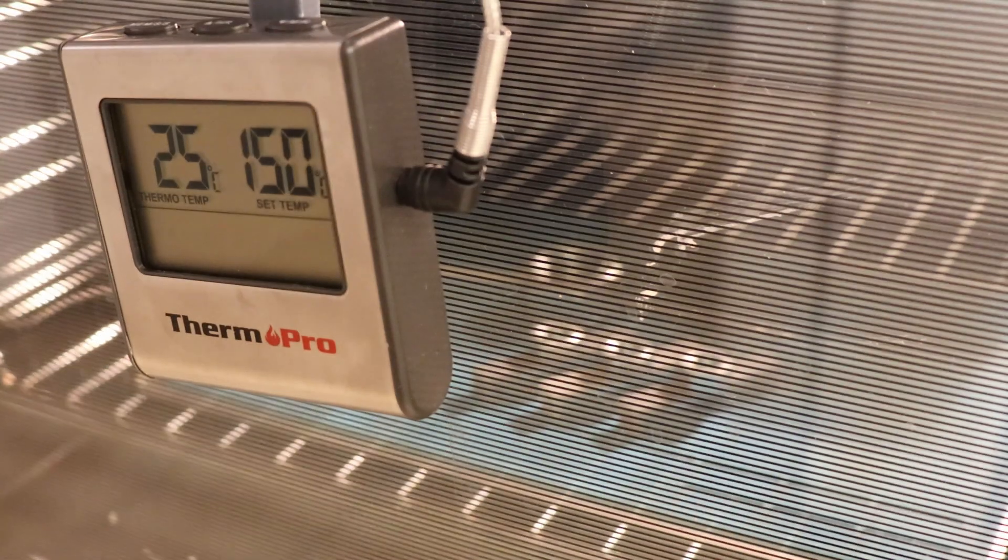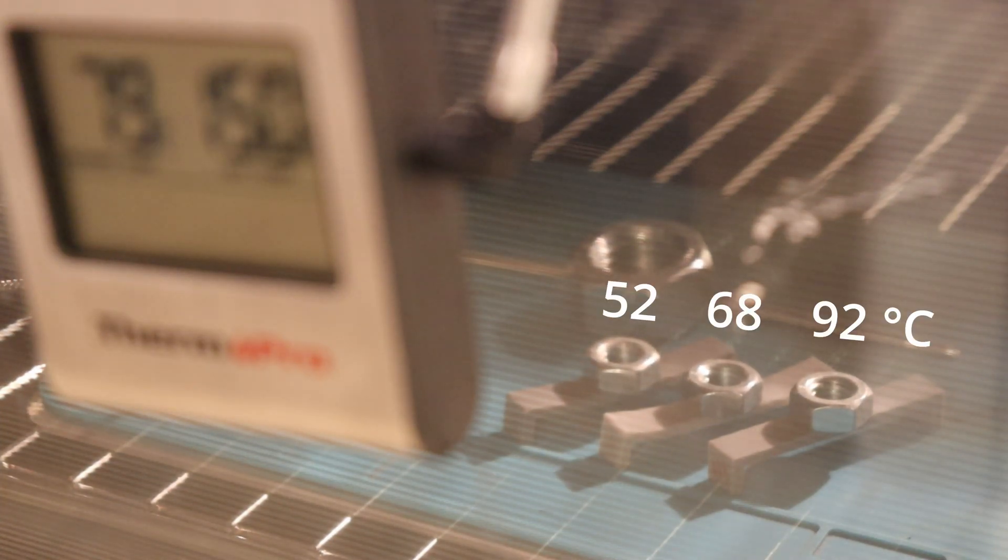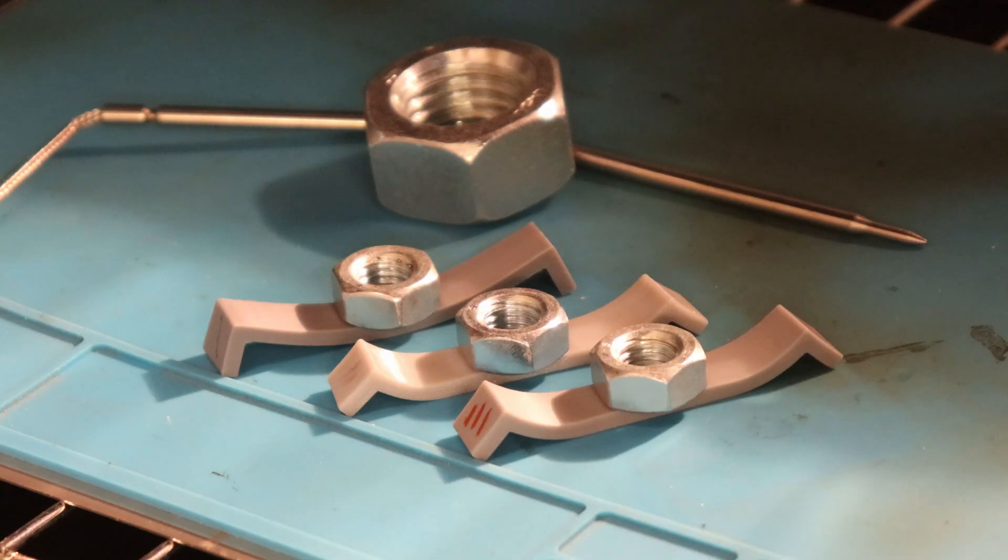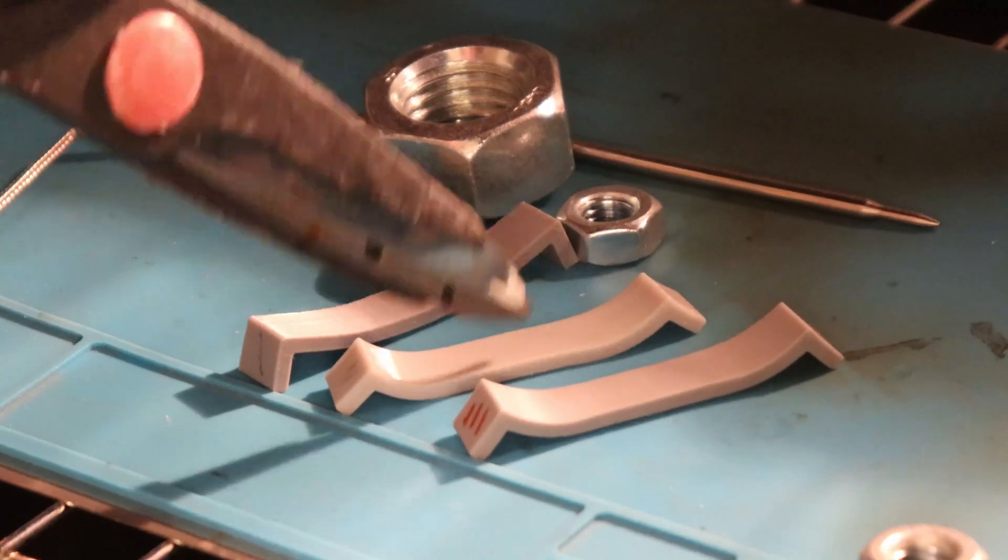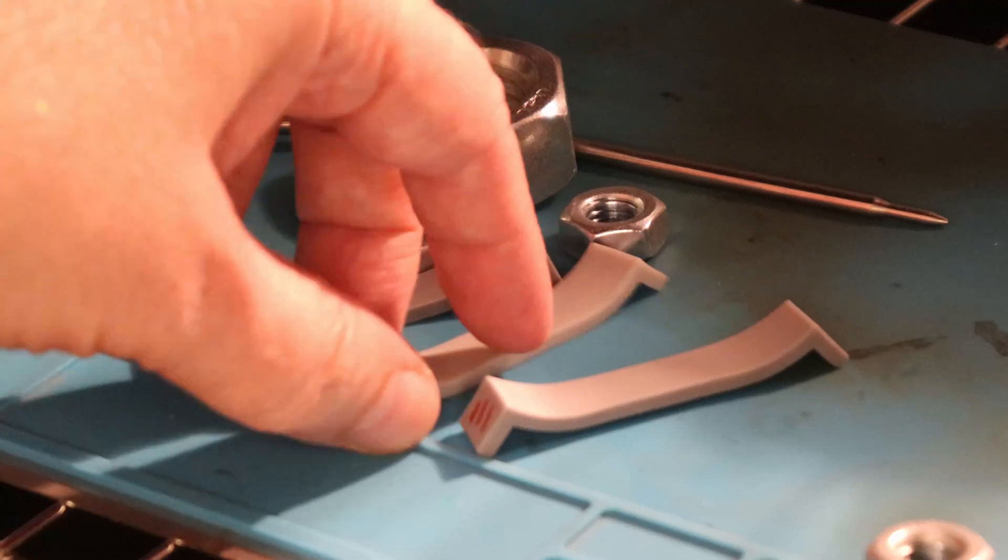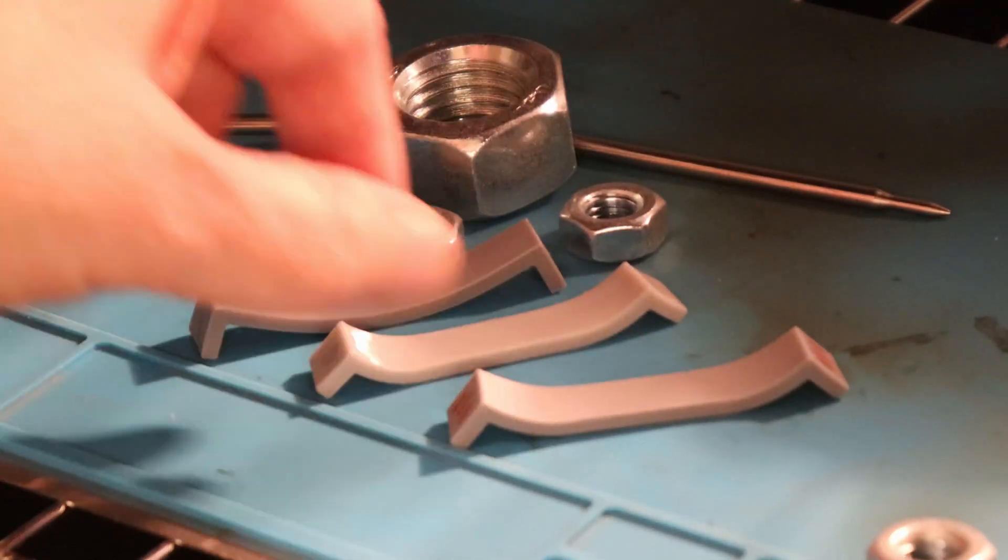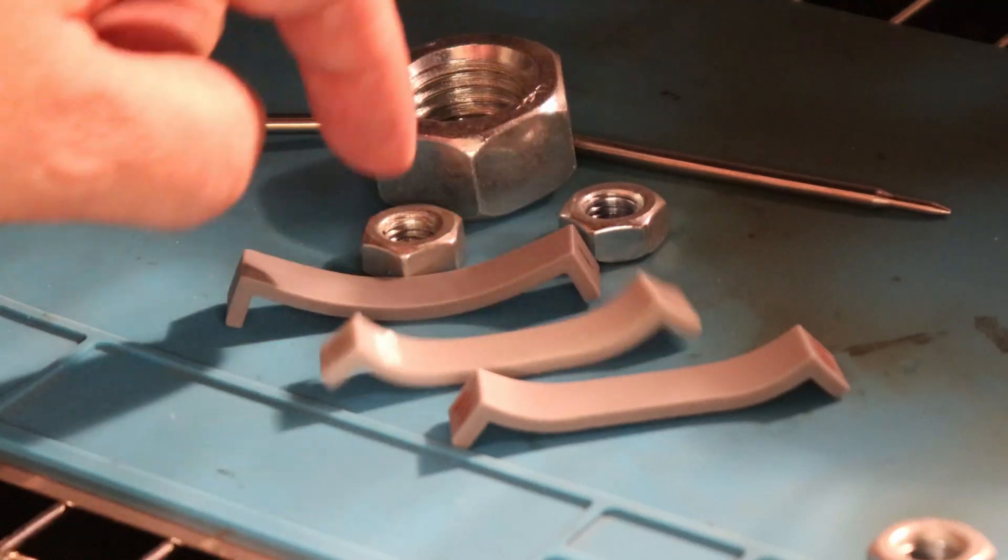The temperature test in the oven, where I want to record the temperature of the first deformation. No surprises here—the first one was the PLA, then PETG and shortly after the ABS. First I'm removing this M10 nut which was the small load, and then I want to see how soft they are. Interesting, for the feeling it looks like the PETG is softer compared to the PLA. Also I can see a little bit more shrinking of the PETG material compared to the PLA, but of course it started to deform at higher temperature.